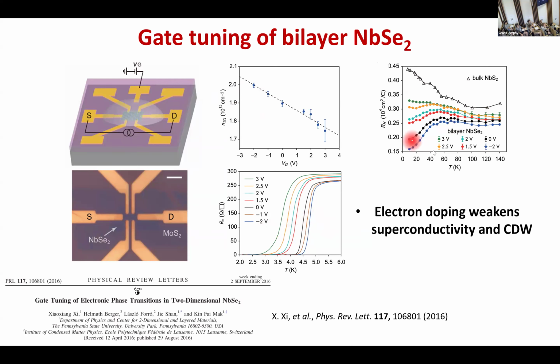And especially here, they measure the Hall effect, because I forgot to mention that for the charge density wave to appear, it reconstructs the band structure, so that you go from a kind of hole dominated system to a more electron dominated system. So there is a bending point just around the charge density wave, and they argue that this bending point shifts to lower temperature when you apply the gate voltage, and essentially it cannot be seen and becomes comparable to niobium disulfide. And niobium disulfide has no charge density wave. So they argue that by injecting a lot of electrons into the system, you somehow suppress CDW.